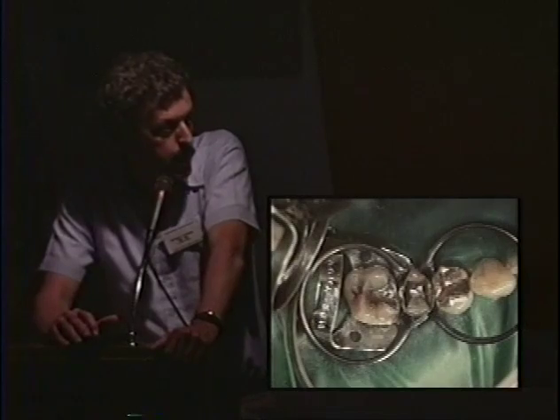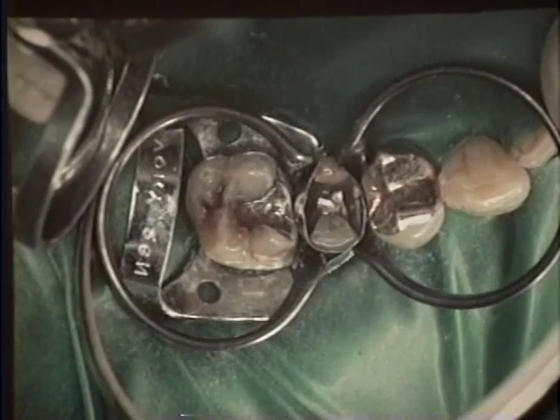Okay, you can do MOD with a Bitine ring, no problem. Just put on 2 of them at once because they arc over the adjacent tooth, not the one that's being restored. Okay. The only thing I can offer as advice based on experience is that if you haven't actually broken the contact between the 2 teeth, then the problem is that the regular sectional matrix won't go through sometimes. It kind of hangs up in there because it's fairly soft. You may have observed this. In that case, yeah, just use ordinary shim stock or a piece of Tofflemire or something, and it'll be just fine. Because in those real tight little preps, the anatomy is not such a critical issue, you know. It's the big preps where the anatomy is so important and you need that sectional. Okay. Now here's a couple little slides here, and then I think I'm really out of time.